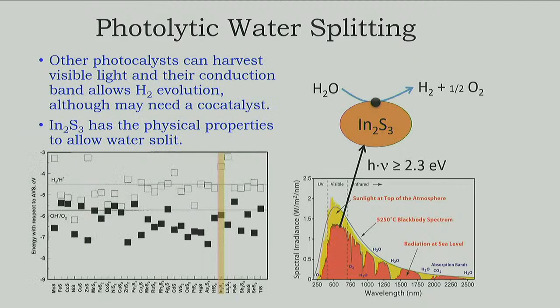This is why we focus on sulfides that are going to absorb visible radiation, which has not only less energy to damage the enzymes, but it has enough energy. When we compare, in this case, indium sulfide, we can see here the conduction band and the valence band, and this is in a very good place for us. It's an N-type semiconductor, and it also absorbs these photons that, reaching the surface of Earth, are much more abundant than ultraviolet ones.